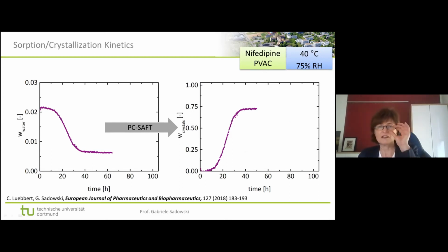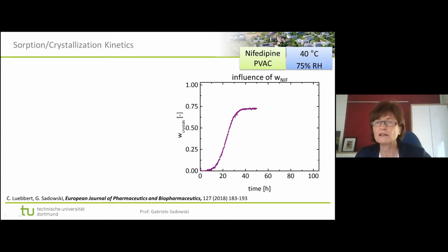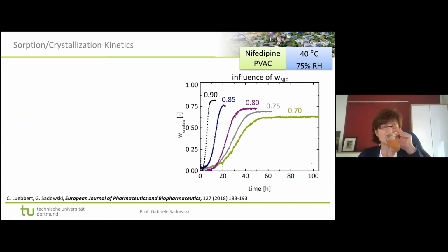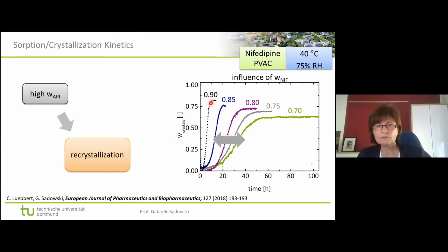And we did the investigation for different API loadings. So we have different API loadings here. The higher the API loading is, the higher is the supersaturation. So that means the faster is the crystallization. And this is also what you see here. Higher API loadings means faster crystallization. And this is now what we can measure, what we really can quantify. So the higher the API loading, the higher the danger of getting crystals in the formulation.